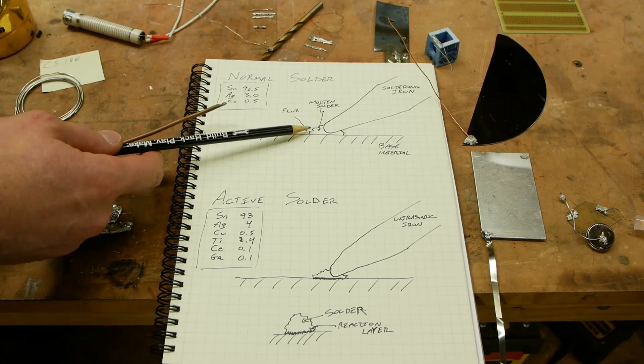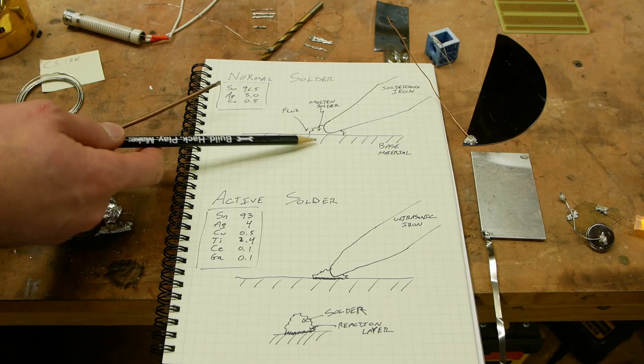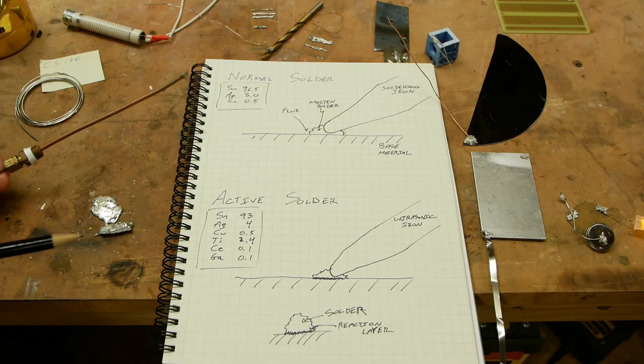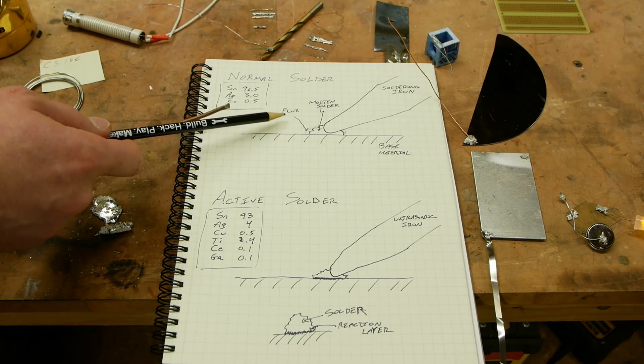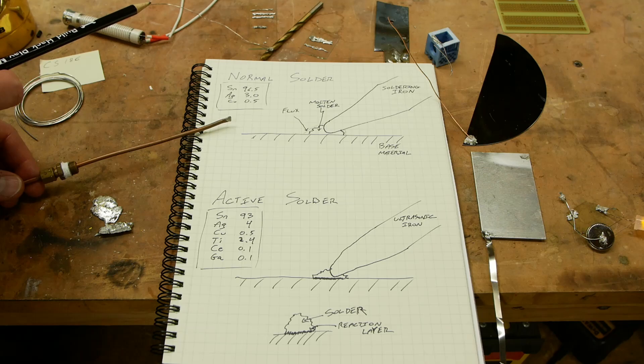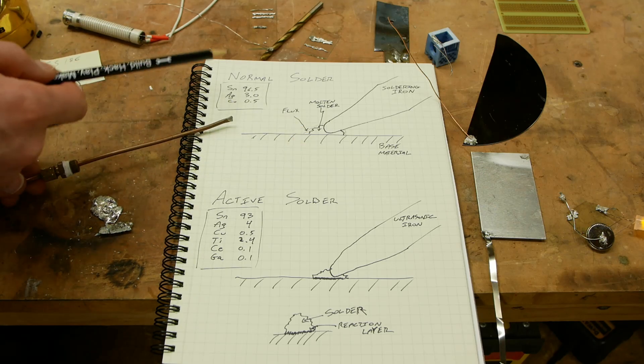And so that's a problem because this copper oxide gets between the solder and the base metal, and that's not a metal, so then this metallic bonding can't work. So the whole point of flux is that we remove the oxide layer.